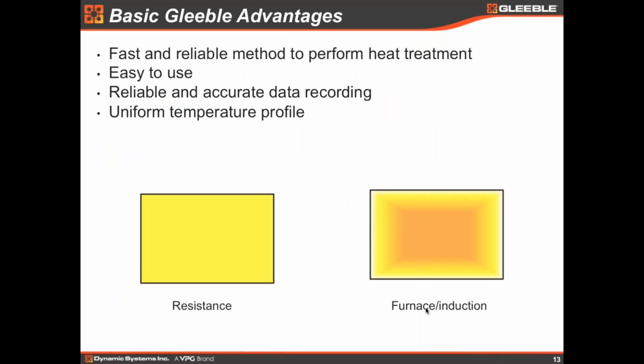So now I'd like to show how Gleeble can be of great advantage to study recrystallization. We have a few points to consider. Firstly, it's a fast and reliable method to perform heat treatment. It's very easy to use, very easy to mount a specimen, start a test and program the machine. One of the most important is that it's very reliable, and there's accurate data recording, very precisely recorded. So we can have several temperature measurements in different positions of the specimen. And maybe the most important is that, because the Gleeble system uses resistance heating, we have a uniform temperature profile. This is very important in recrystallization studies.